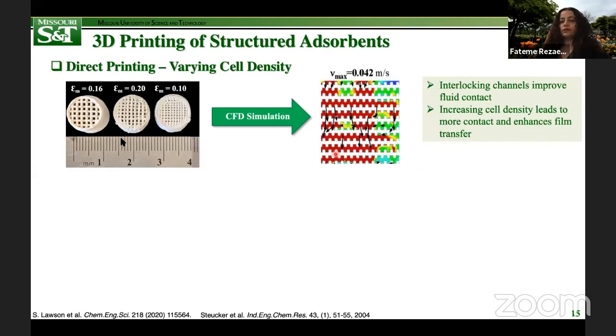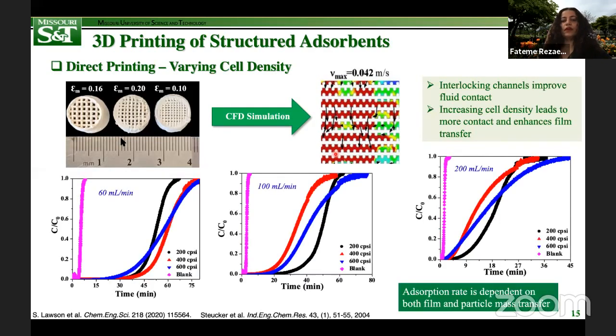So here, as expected, increasing the cell density gave rise to enhanced film mass transfer coefficient, mainly increasing the cell density from 200 to 400 nearly doubled film mass transfer at every velocity investigated here, 60 to 200 mL per minute. Similarly, by increasing the cell density from 400 to 600 CPSI, we observed around 30% enhancement in film mass transfer coefficient. However, and as apparent from the breakthrough profiles, here the enhancement in film mass transfer didn't improve adsorption kinetics.